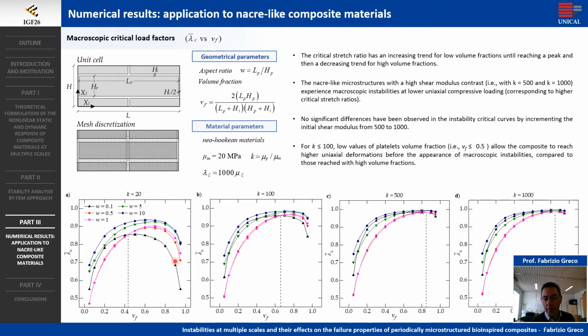As can be seen in the following picture, in the nacre-like materials with low shear modulus contrast K, the macroscopic instability critical curve peaks are reached for intermediate values of the volume fraction, while for high values of K, the peaks are reached for higher volume fraction. In the general cases of low K, low values of platelets volume fraction allow the composite to reach higher uniaxial deformations before the appearance of macroscopic instabilities.